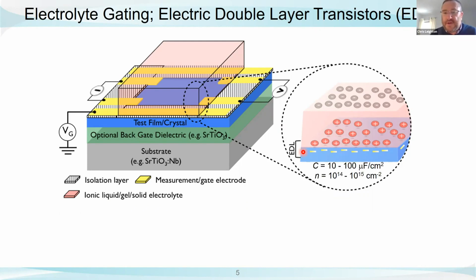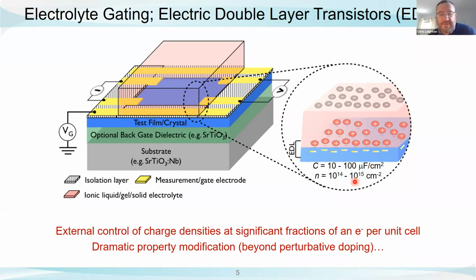It generates very large capacitance, as much as 100 microfarads per square centimeter. And if we then just use Q equals CV, that translates at just a few volts to as much as 10 to the 15 electrons or holes per square centimeter. It's 100 times more powerful, roughly speaking, than a conventional MOSFET with a standard dielectric. So what this device gives us is an external means to apply an electric field and accumulate charge densities that are at a significant fraction of an electron or hole per unit cell in most materials, okay?